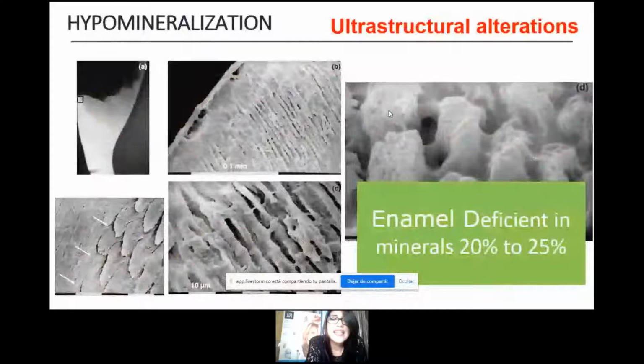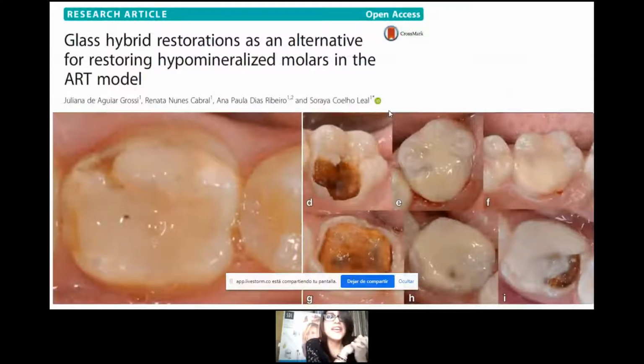So let's check. This hypomineralization has enamel deficient in minerals by 20 to 25%. Okay, so you will have a risk in this lesion to have caries around the lesion, the molar incisor hypomineralization. The other thing is that in dentin, you will have more zones of interglobular dentin. Interglobular dentin is slightly less mineralized. So check it, okay? It's important to know the histology about this. So if you decide to use glass ionomer in molar incisor hypomineralization, you may have some failures.